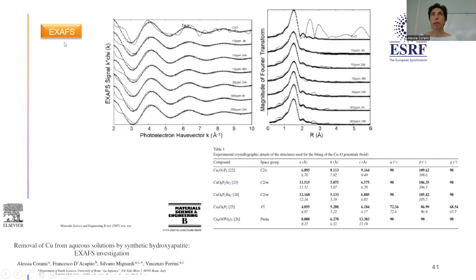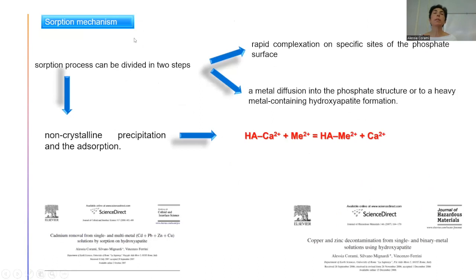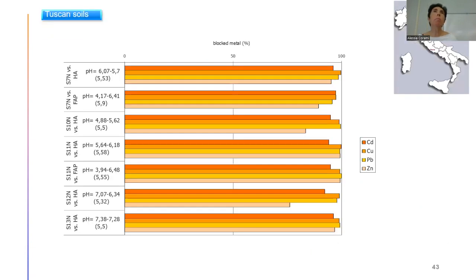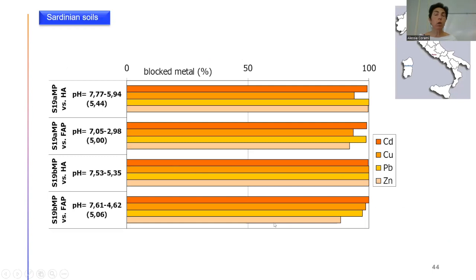So we analyzed our solid samples with EXAFS, and from the data that we get, we can say that we observed a fast complexation of metals on the surface of the phosphate. So we designed a sorption process that could be divided in 2 steps. We have a first rapid complexation on the specific sites on the surface of the phosphate, and then a diffusion into the phosphate structure, but with a non-crystalline precipitation. So at the end, we have a phosphate enriched with these metals and the release of calcium. And then we applied our phosphate to the Tuscan soil with a good result. And also for the Sardinian soil, we have the same good results.